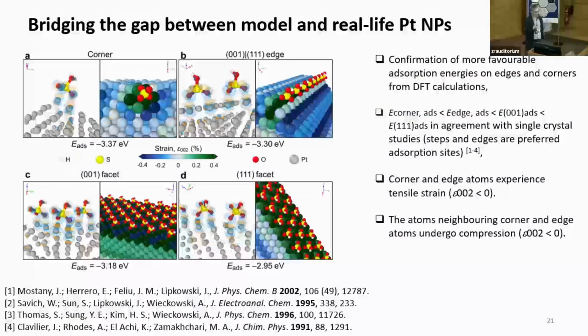We also got a very nice confirmation from the work of Corentin by DFT, where he could show that the anions are on average preferentially adsorbed on edges and corners. So you see there is a very negative adsorption energy for the sulfate atoms on the edges, on the corner, sorry. And there is almost 0.2 eV versus the 001 facet, and almost 0.4 eV. This is huge compared to the 111 facet. So we think that we have this preferential adsorption of anions on the corner, and that causes an expansion first of these atoms here. And again, as a response, there will be a compression on the neighboring atoms. So here again, we see this heterogeneity in strain distribution, but this time at the atomic scale.